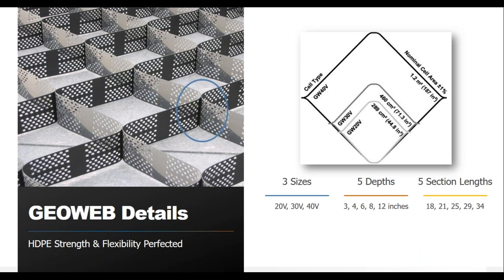The ultrasonically welded seam, where all the connecting points are located, is very important to the function of a Geocell. The stronger the seam strength, the better the performance of the Geocell. A strong seam allows for better long-term performance. Geocell is produced using high-quality, virgin, high-density polyethylene resin for consistently strong welds at the seams, while also maintaining semi-rigid ductile properties, high-stress crack resistance, overall toughness, and long-term durability. Geocells do not use fillers or exotic polymer alloy blends, which can reduce weld strength as offered in some competing products.